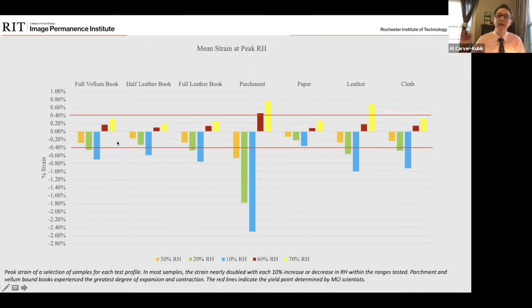What I did is I took the data point at the end of the soak period at our peak RH or lower end of RH. So the very end of our profile in which we decreased to 30% RH, I grabbed that data point and graphed it. And so I have a full vellum book, half leather book, full leather book, parchment, paper, leather, and cloth. And you can see here are the desorption profiles. Again, 30%, 20%, and 10%. And the absorption profiles, 60% and 70% RH. In each of these cases, our strain doubles with each decrease or increase in RH. So here we have a doubling in negative strain, and here we have a doubling in positive strain. So expansion and contraction.